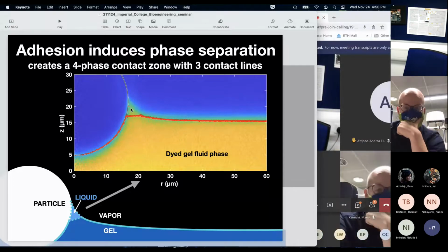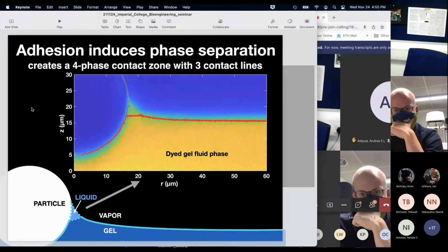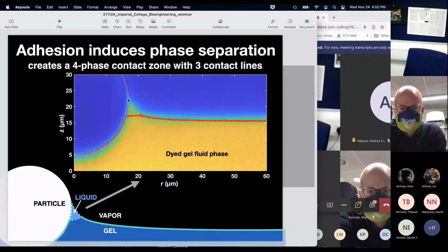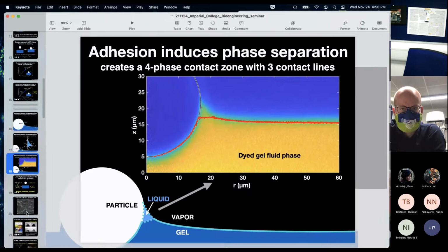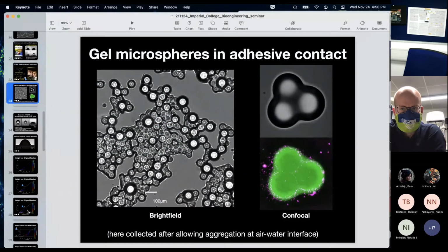I think you mentioned some questions about when there is fluid and when there's not. There's always probably some fluid. One of the things that came out of some experiments I didn't tell you about involved taking the sphere and pulling on it, withdrawing it from the surface. We see that if you really put the system into tension, the fluid gets sucked back in. So there starts to be less and less of a phase-separated fluid if you're pulling on the surface.